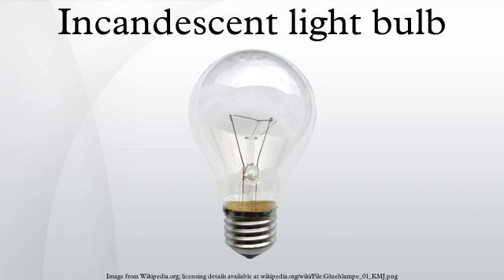The upper temperature limit for the filament is the melting point of the metal. Tungsten is the metal with the highest melting point, 3695 K. A 50-hour life projection bulb, for instance, is designed to operate only 50 degrees Celsius below that melting point. Such a lamp may achieve up to 22 lumens per watt, compared with 17.5 for a 750-hour general service lamp. Lamps designed for different voltages have different luminous efficacy.